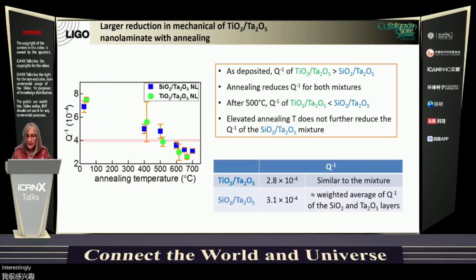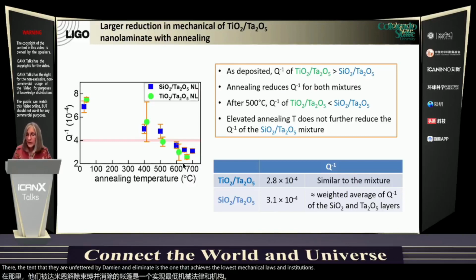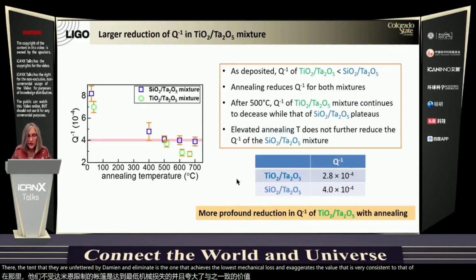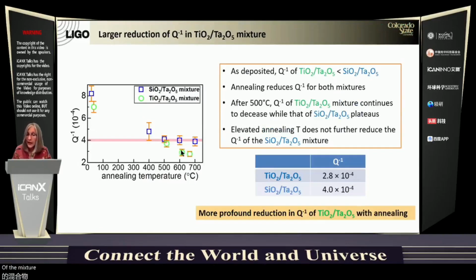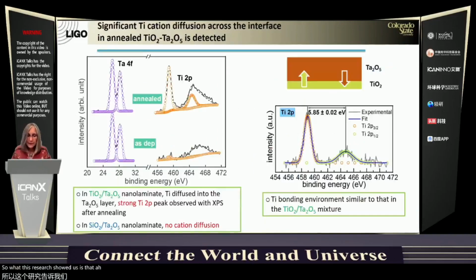Interestingly, the tantala titania nanolaminate is the one that achieves the lowest mechanical loss, and it achieves a value that is very consistent to that of the mixture, as can be seen here. These are the results of the mixture compared with the nanolaminate. So what these results showed us is that the diffusion that occurs in the titania doped tantala is actually what drives the reduction in mechanical loss.